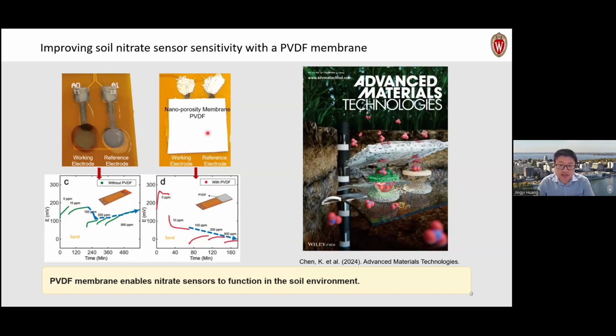However, after we place this membrane, which can create a humid local environment, we place our sensor into the soil samples. In this case, we have a sandy soil. With different nitrate solutions, increasing from 0 ppm to 500 ppm, once the sensor and the soil environment reach equilibrium, which takes roughly half an hour, at the equilibrium point the nitrate concentration has a linear, negative relationship with the voltage or the potential of the electrode. Based on that, we can demonstrate the sensor works in the soil environment in the lab.